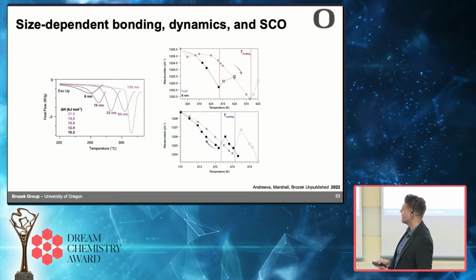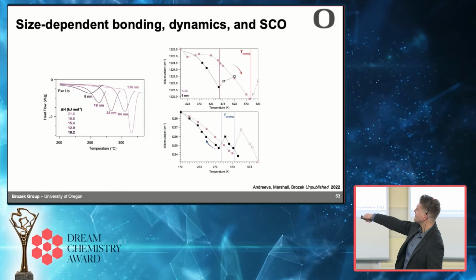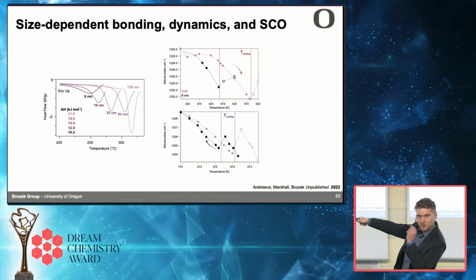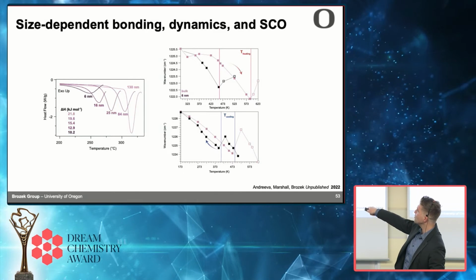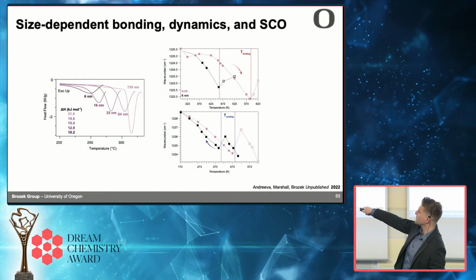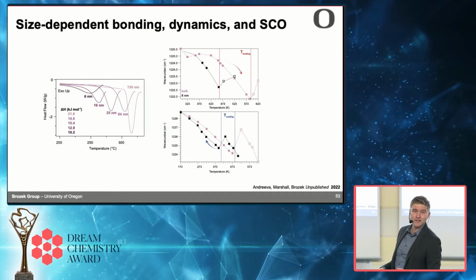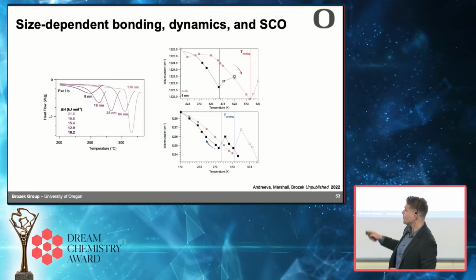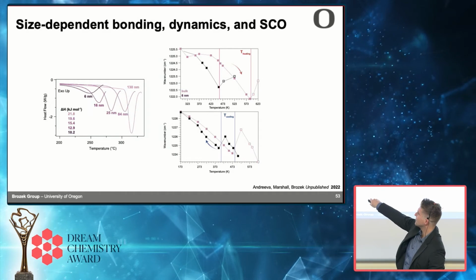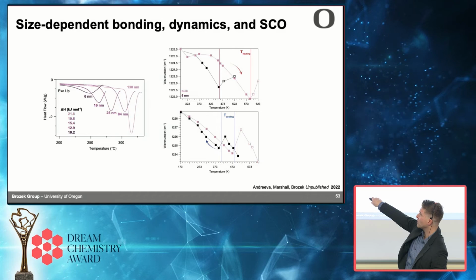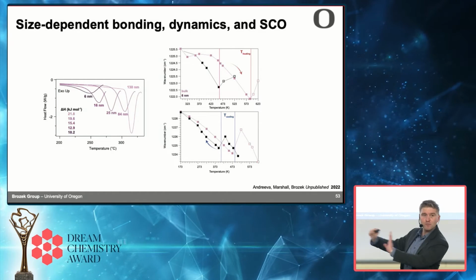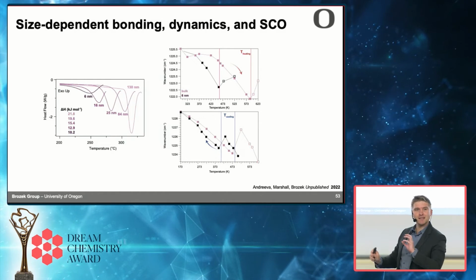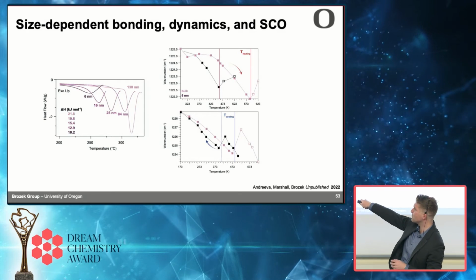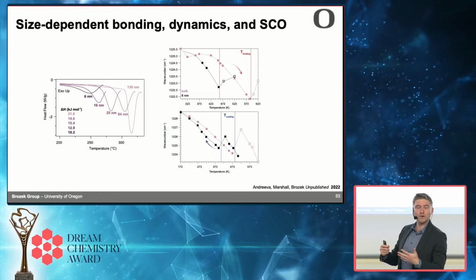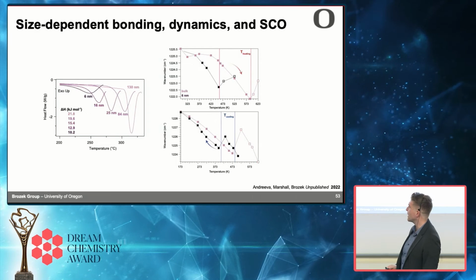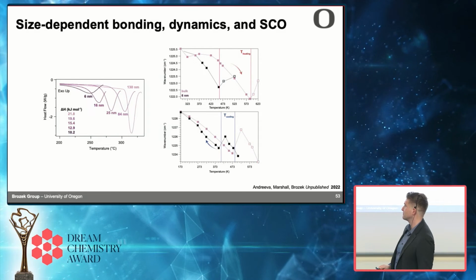And we see in the calorimetry data, so every time you get a dip here, it's telling you that's where the spin crossover temperature is occurring. As we move from 130 nanometers to just 6 nanometers, we see that transition drops by over 50 degrees, which is really cool. In the IR data also, in the pink is that redshift that I showed you previously for the bulk material. And when you make it smaller, everything moves. And so it's consistent again with this idea that you make a particle smaller, that slope becomes steeper. And one way to interpret that is the crystal's actually becoming more flexible. The spin crossover is easier to happen.